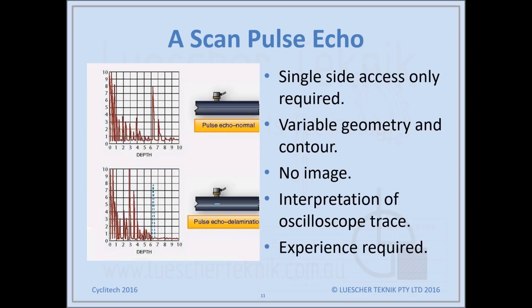If we look at this particular defect here, which is approximately mid-plane of the part, it's coming up right about here. So it's about half the thickness of the part. If the back wall is coming up at around a depth of 6, here it's coming up at about 3. So we know that the indication is about halfway through the part.